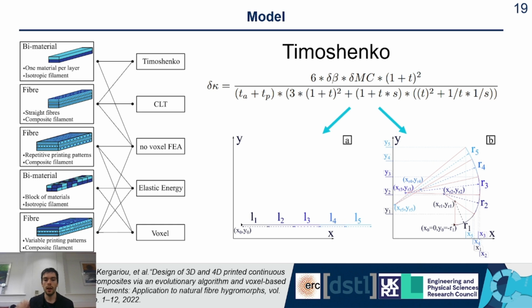Then if you want to refine even more and have more local understanding of the behavior of your material, elastic energy and voxel-based modeling are interesting because you can define properties of your material very locally. For instance, you can CT scan your material, assign mechanical properties to every single voxel that you obtain, and build an actuator from this technique.